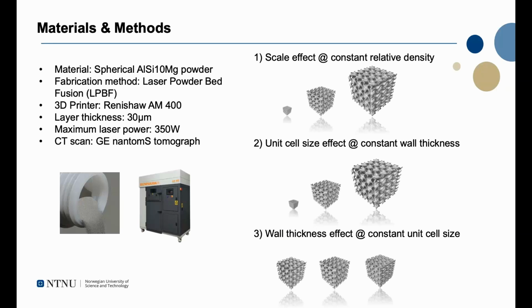First, the scale effect, keeping a constant relative density for all the lattices but varying the unit cell size and the wall thickness. The second is the unit cell size effect, basically changing the unit cell size but keeping a constant wall thickness. The third category is the wall thickness effect, having a constant unit cell size but changing the wall thickness. So basically all the parameters of the lattice structures have been investigated comprehensively in this case.